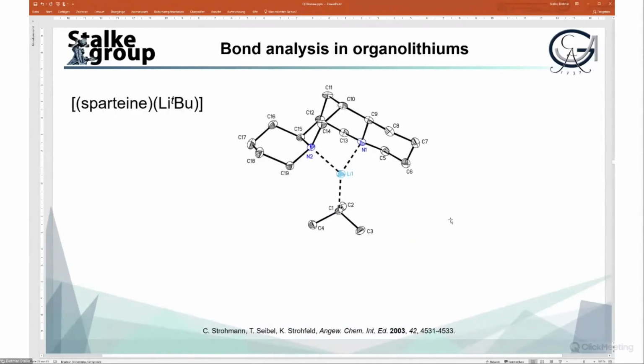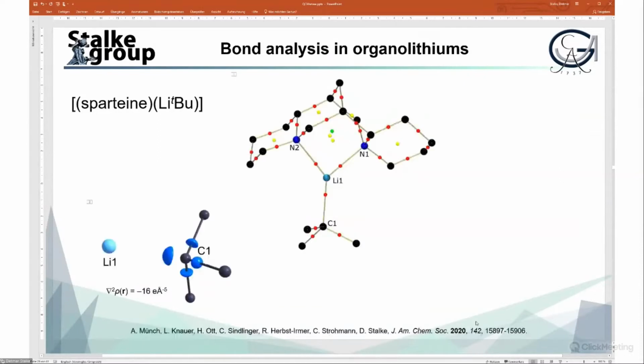So how about the monomer, which was determined in, I'm reluctant to say a routine structure determination, so say a less highly resolved structure determination, done earlier on by Carsten and Katja Strohfeld when we worked together in Würzburg. That was the structure, and we had the chance to look at it with more sophisticated techniques and better machinery these days. So we found the bond path as well, and we had a huge lump of density pointing directly to the lithium, and this is, of course, now very nice to compare with the lithium-nitrogen bonds.